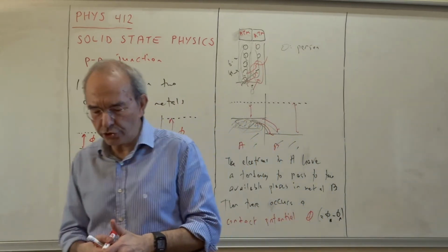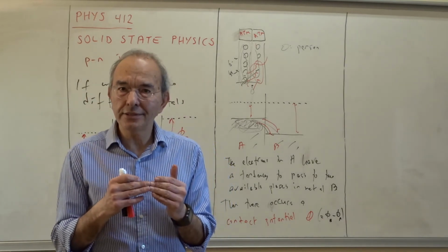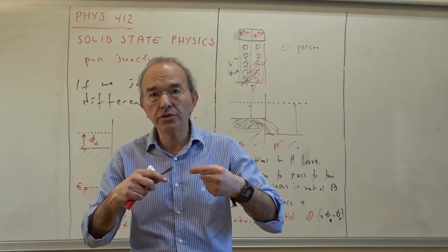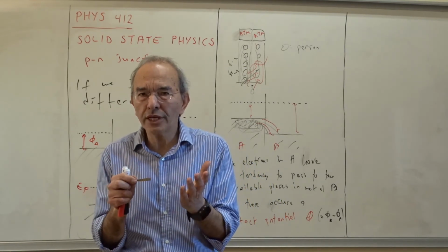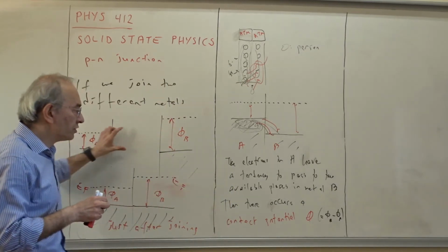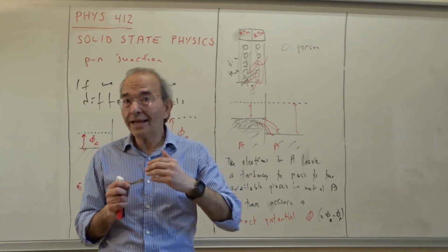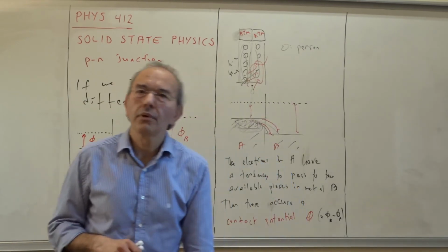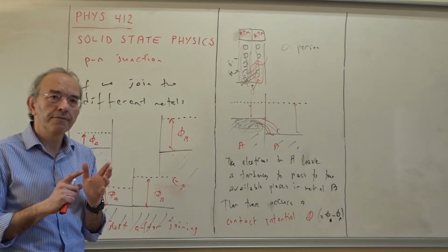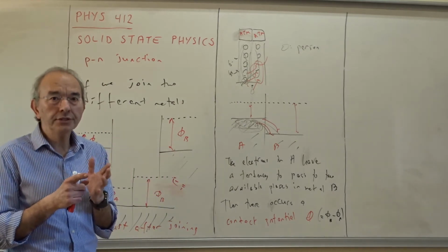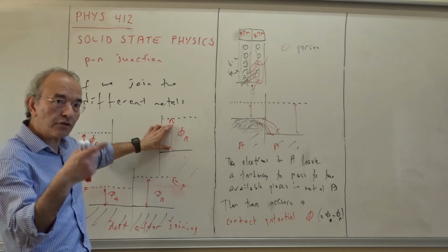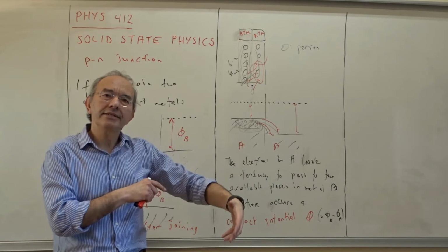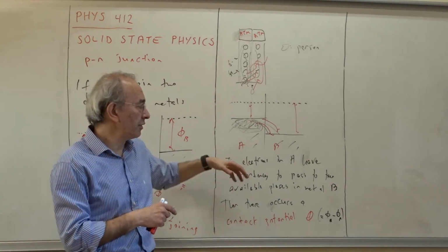Of course, if we join two similar metals, a silver teaspoon with another silver teaspoon, there will be no contact potential because each one would have the same work function. Since they are dissimilar metals, metal A and metal B, and the work function is peculiar to the type of element, therefore there is a difference, and because of that difference, the more energetic ones in one try to go to less energetic places, available positions in the other one.